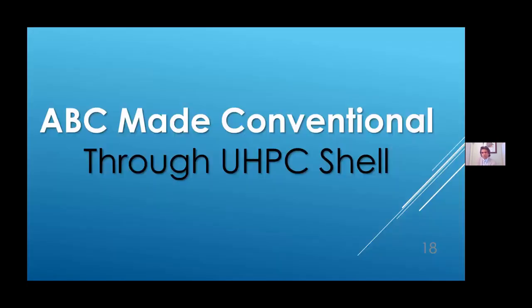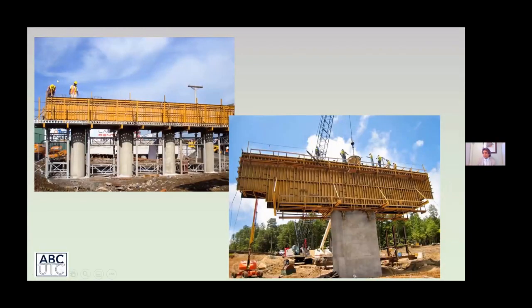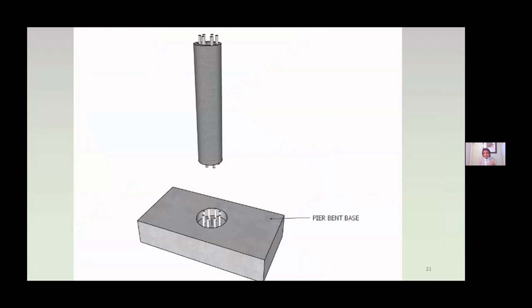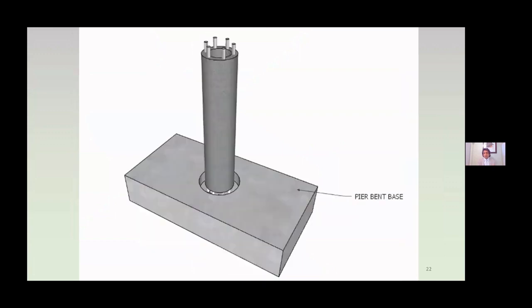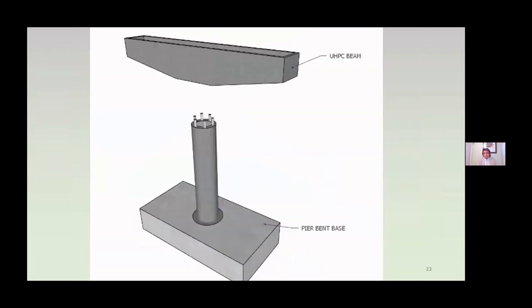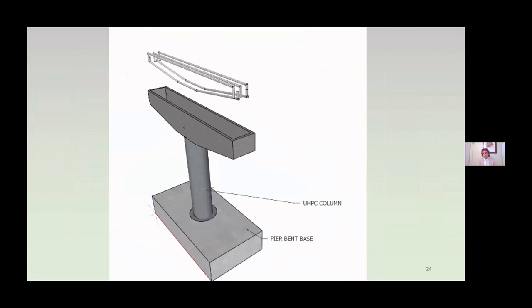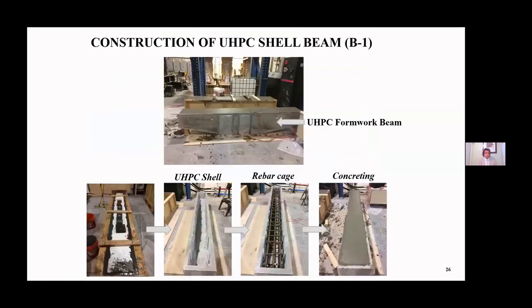Another concept we have come up with is replacing the formwork with the UHPC. So another way, rather than building my formworks using what you see over here, use a UHPC shell. Bring it to the field, connect them together, and then place your reinforcement and fill it with the lightweight concrete. So this is schematically basically showing this. You precast basically a shell, representing a column. You bring it over here, you connect them using the UHPC connections. Here's a cap beam. You put it on top of the precast shell for the column. You put the reinforcement, you place the concrete, and you're done.